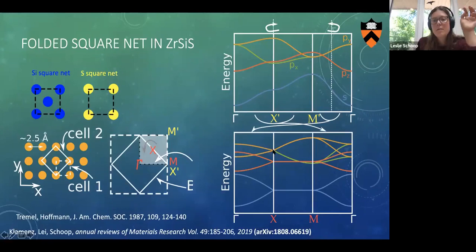So with the 6 electrons, we pin the Fermi level at this energy. And with 8 electrons, we would be up here. So what the hypervalent bond does is it stabilizes the 6 electrons, which usually would not be stable. We always would want it to go to 8, and it gives us the chance to put the Fermi level at the crossing point.